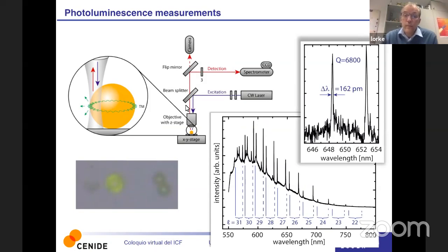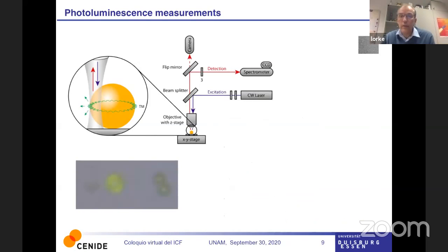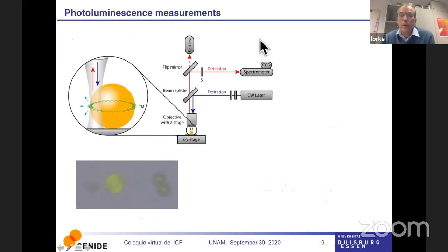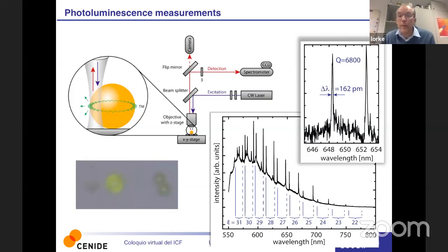These resonances are quite sharp. You talk in this field about a quality factor that is here close to 10 to the 4, or in terms of the uncertainty of the wavelength, it is 162 picometers. So, I mean, the spheres are approximately, let me see, here was a scale bar, approximately 5 micrometers large. So this is a spectroscopic technique where you get quite high precision.